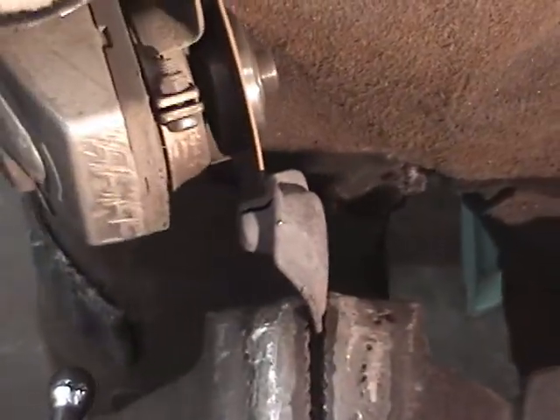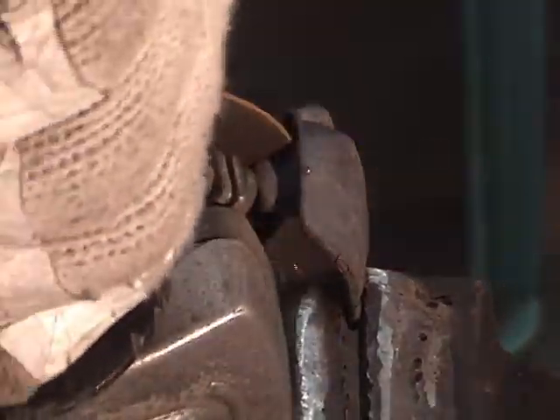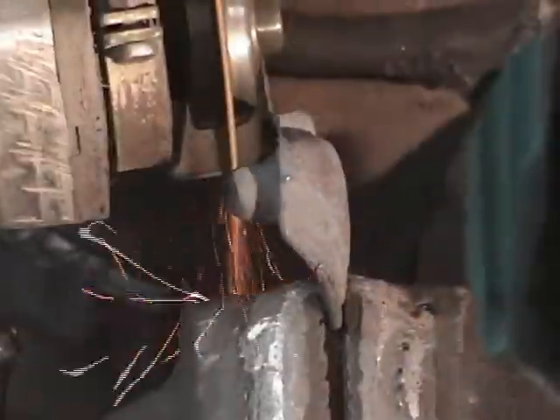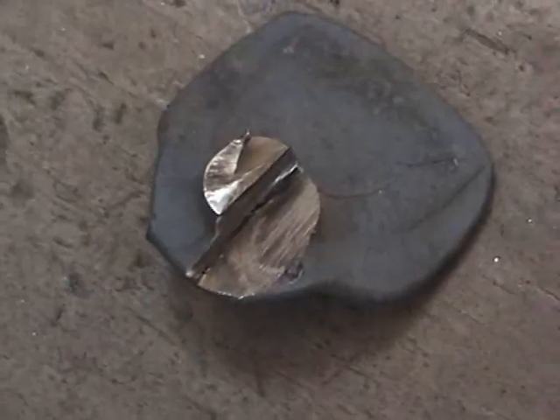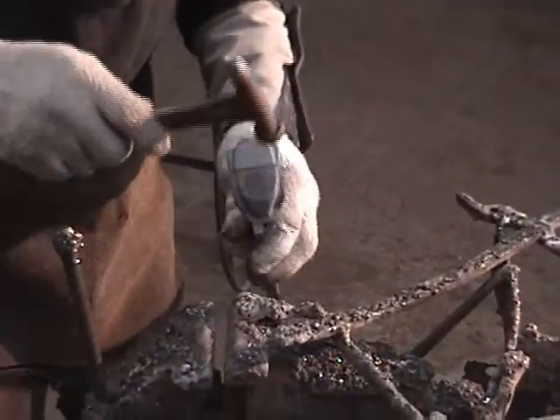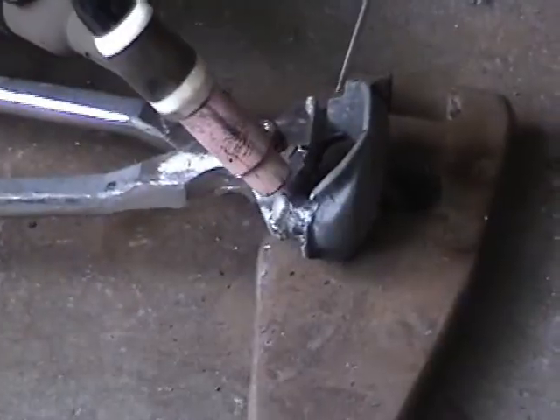We use an angle grinder with a cutting disc attached to remove 1/2 of the diameter of the stump of the blade. This is done so that when the H13 blade is welded on, we can use a Z-weld for a stronger weld instead of a straight line weld. Otherwise, your nipper blade might break off at the weld, but done in this way, that never happens.